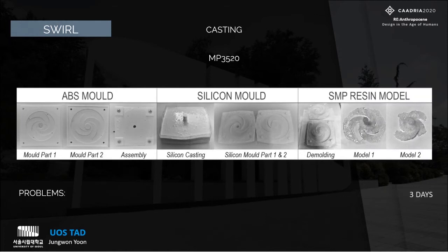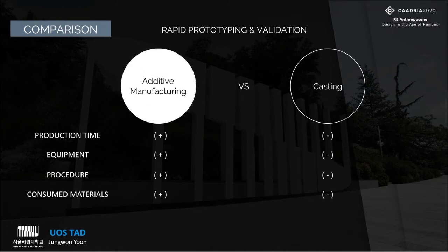Due to the volume of the prototype, the curing time for SMP increased significantly from the guided duration up to 3 days. Also, the complicated geometry turned out to be not adequate for casting. From experiments with the 2 different manufacturing methods, although 3D printing was difficult to conduct for SMP models, it was demonstrated that 3D printing is superior to casting in its advantage of production time, required equipment, procedure, and consumed materials. This comparison informed us to revisit the system and the SMP design.